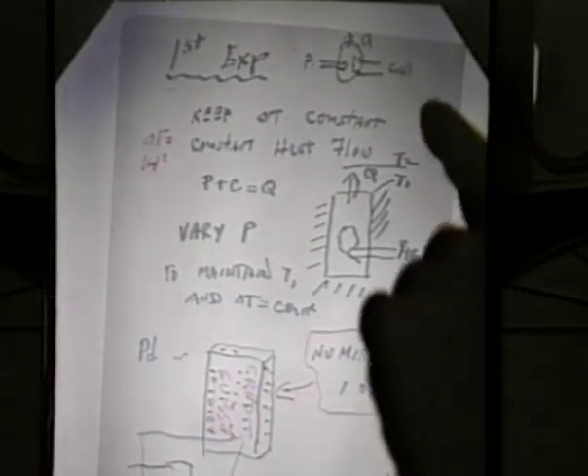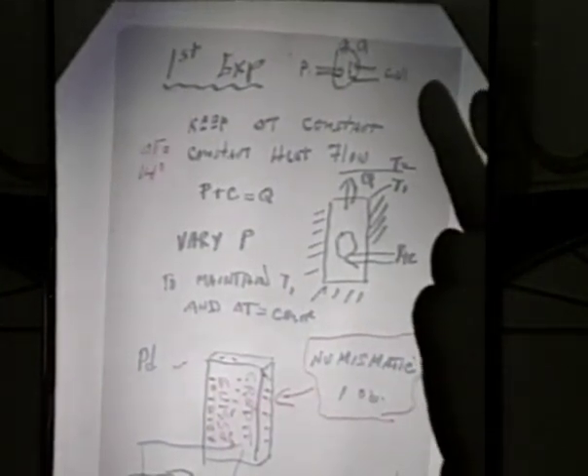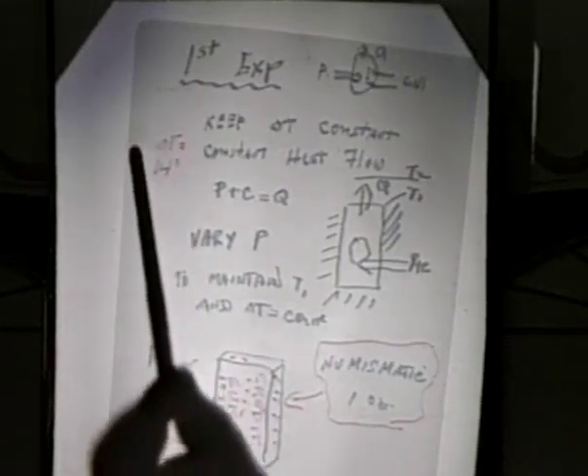All right, our first experiment, what we did was, as I said, have a black box, maintain a constant temperature difference between the inside and outside, and allow the heat flow to be constant. We had the power going in for the cell and a calibration resistor inside the aluminum enclosure, so that the sum of those two would remain constant. In other words, the power P plus the cell current power equal the heat flow out would be the balance equation. As we generated or absorbed power in the cell, we varied P to keep the temperature constant and maintained basically a temperature difference between the inside and outside of about 14 degrees centigrade.